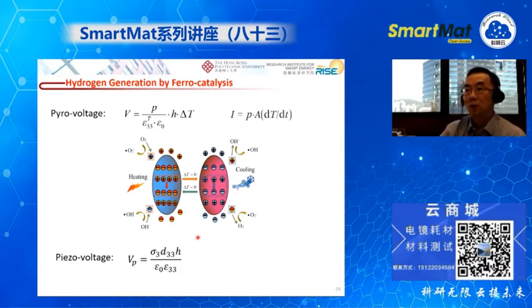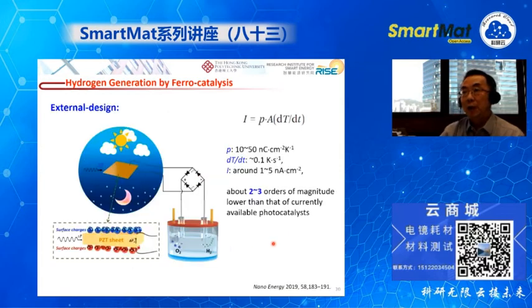So this mechanism is quite similar to photocatalysis. But if you compare it with photocatalysis, then we find a problem. And this is the early design for making use of the pyroelectric material for the water splitting. You can see when the temperature of the material is being changed, it generates a pyroelectric voltage. And if the voltage is large enough, it can split the water.